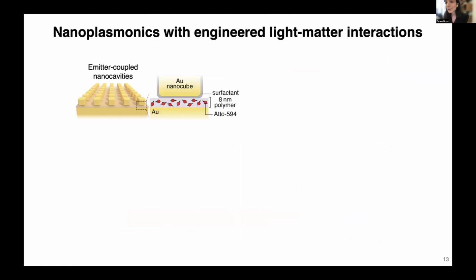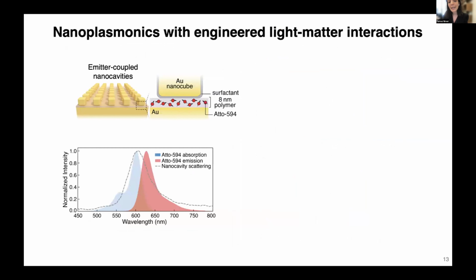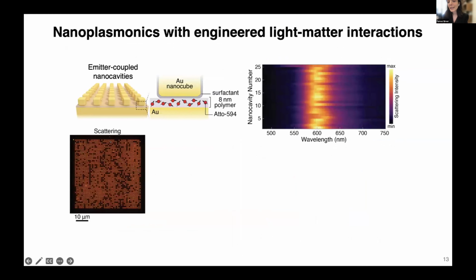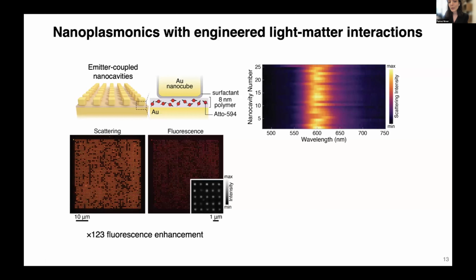To show the integration capability of our approach, we integrated our plasmonic cavities with molecular emitters, designing the cavities to have resonance that overlaps with the absorption and emission spectra of the particular molecule that we're using here. Here's an example of an array of such devices. You can see through this scattering measurement of an array of 5 by 5 of the devices that the response is quite consistent and reproducible and uniform through use of fluorescence imaging over a large area.